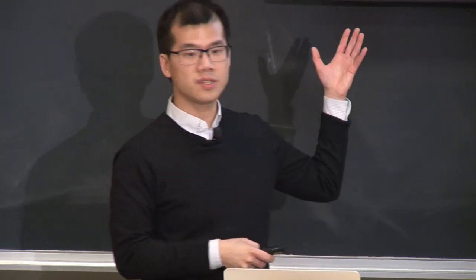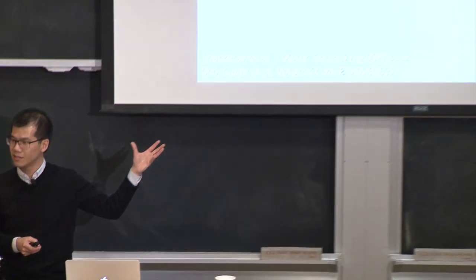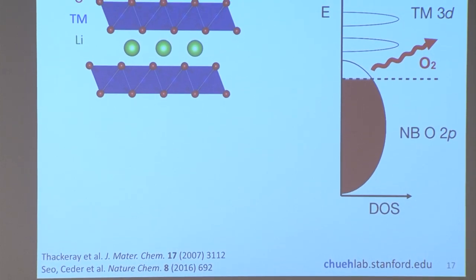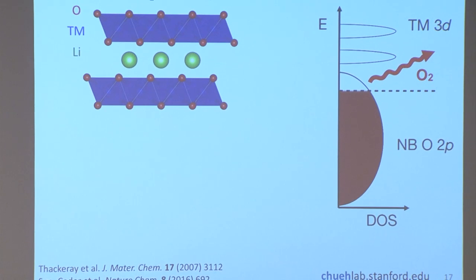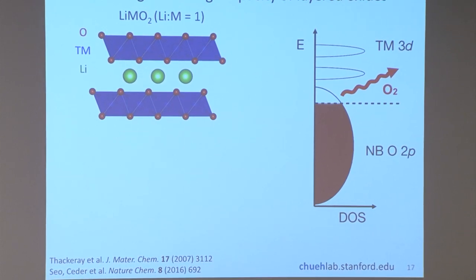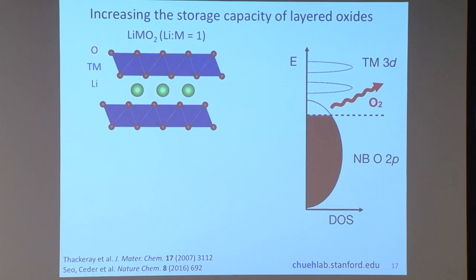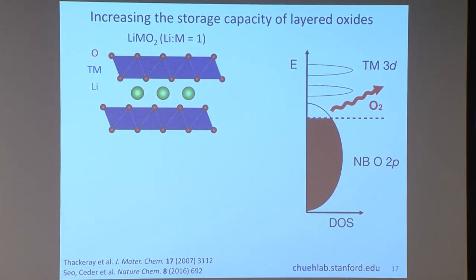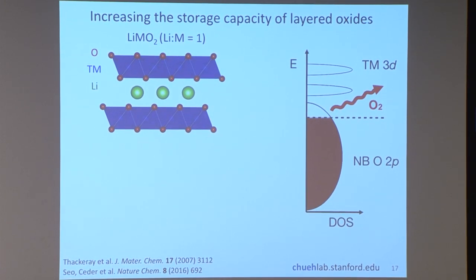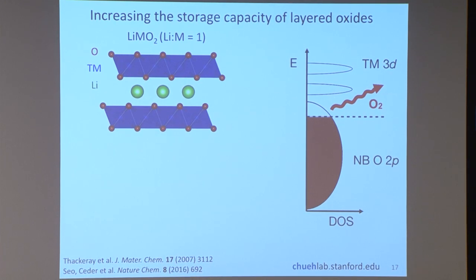So let me get into some specifics here on the material chemistry. So this is the perfect material, say lithium metal oxide. You have alternating layers of oxygen, metal, and lithium. And what I want is for the material to stay this way after I remove the lithium and I put the lithium back. This is how you get a reversible storage mechanism.